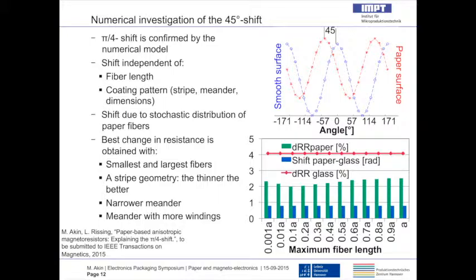So here also the roughness of the fibers is not modeled, so the only parameter present in the simulation is the fiber network topology. And here again we confirm that 45-degree angle shift. What we found is that this shift is independent of the fiber length. Whether you have small fibers or long fibers, you still have that 45-degree angle shift. If the coating pattern changes from a square, fully coated sample to a stripe to a meander with different dimensions, that pi/4 or 45-degree angle shift is there.